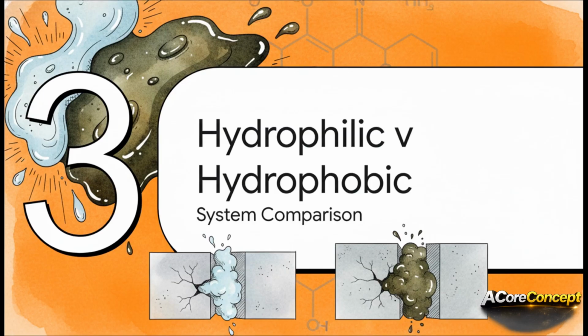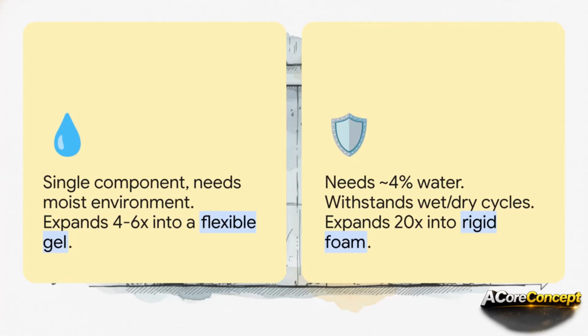Okay, Section 3, hydrophilic versus hydrophobic systems. Let's break this down. You absolutely must choose carefully here based on your specific environment. Hydrophilic grouts are typically single-component systems. Now, hydrophilic means they literally love water. They require a continuously moist environment even after curing, otherwise they might shrink. They'll expand about 4 to 6 times their original volume, forming a flexible gel or foam, which makes them excellent for continuous active leaks. On the other hand, hydrophobic grouts, the water haters, require very little water, only about 4% to react.